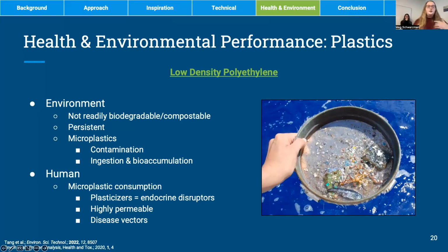So starting with low density polyethylene, the main concern with low density polyethylene is environmental persistence, which leads to the breakdown into microplastic particles. So we've considered, as Scarlett mentioned earlier, biodegradability and compostability were very important parameters for SWAY. So in looking at all of our different strategies, we considered the OECD 301B biodegradation test, which sets a standard for 60% carbon dioxide conversion in 28 days. And we also considered the ASTM standard that was mentioned earlier, which sets a standard for 90% conversion in 180 days.